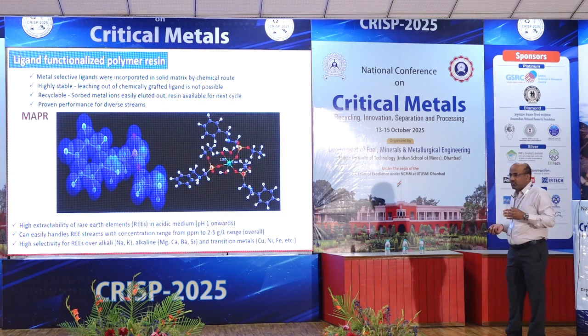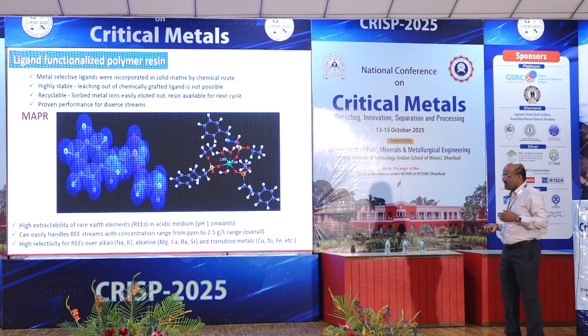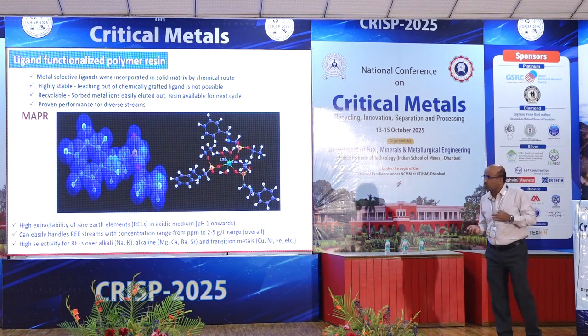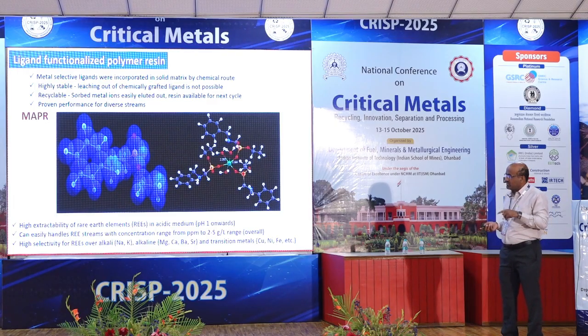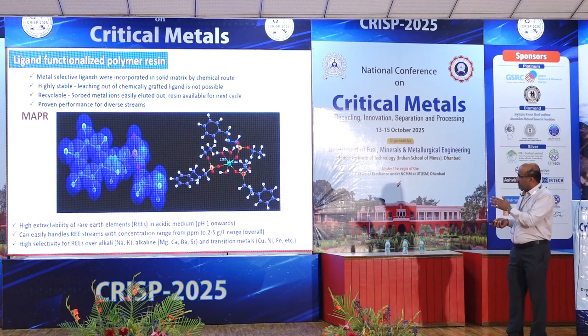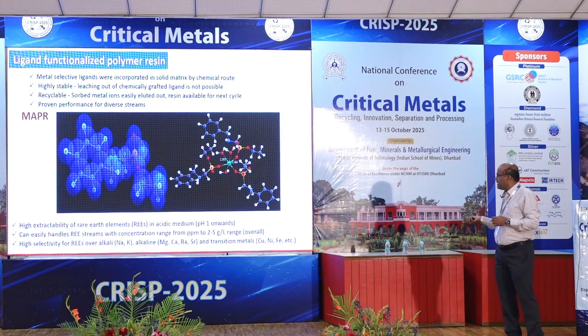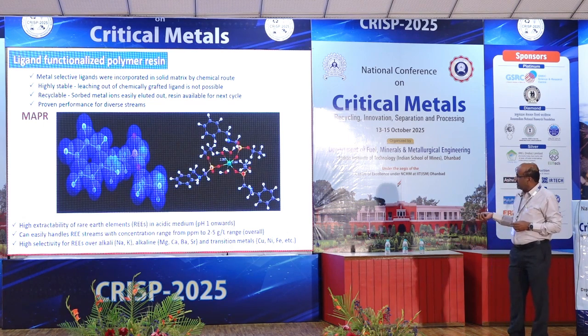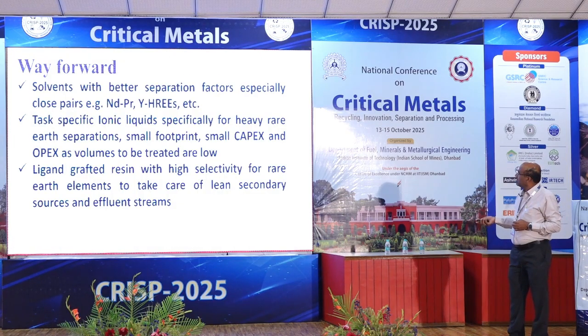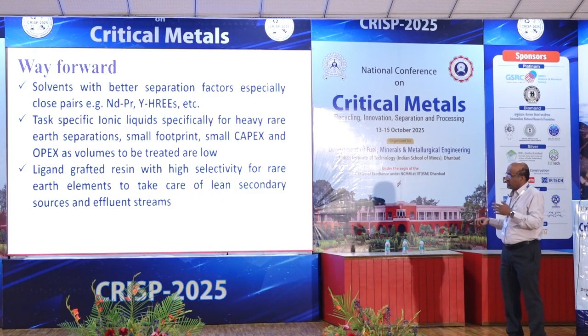In some of the streams we have rare metals, but the acidity is like pH 1 or so. So we want a resin which can work at these acidities, which can extract only rare elements and leave the alkaline and transition metals. With this resin we have got very good results, and it can work from 2 sub ppm to 2 to 5 gram per liter overall rare earth chloride, and it can reject even the iron and aluminum. So this is what I want to put forward, that we can have some solvents with better separation factors, even ones which are not available worldwide.